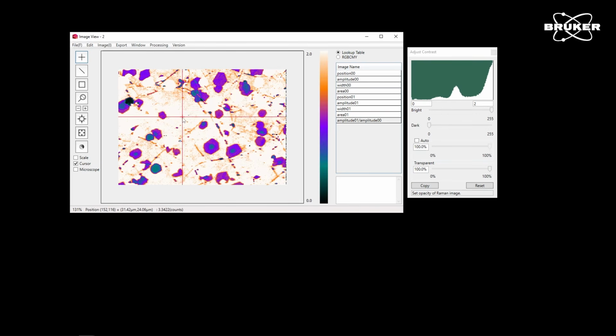With that, the label of it being a CVD Bilayer graphene is wrong because most of the area that we see here is a monolayer. With our fast imaging technology, we can even extend this measurement to bigger areas to truly confirm the inhomogeneity. But this fast measurement already showed us that this sample is not really useful if you rely on a bilayer sample.